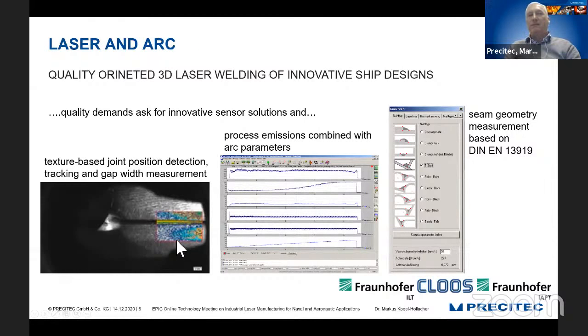So the idea here, which was developed by Fraunhofer ILT, was a texture-based seam geometry and tracking and gap measurement system. We used the sensor technology to measure process emissions, to directly tell something about the weld in situ. And we also had a seam geometry sensor based on laser triangulation to measure the resulting seam geometry based on the DIN EN 13919, which is a norm which is only for laser seams.